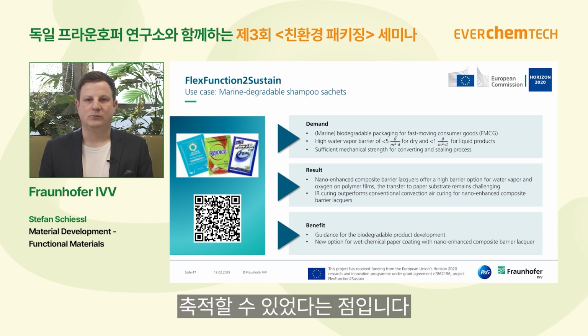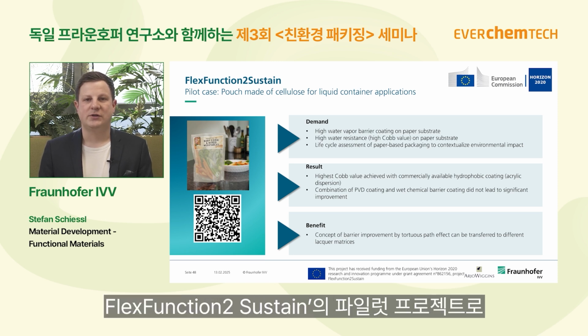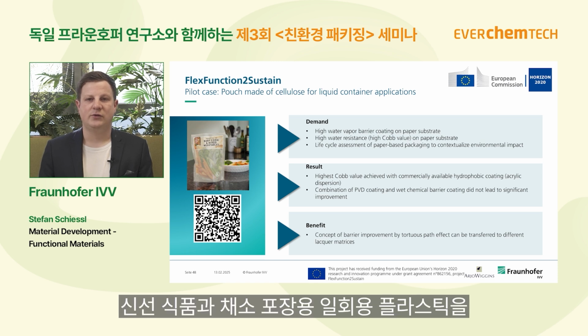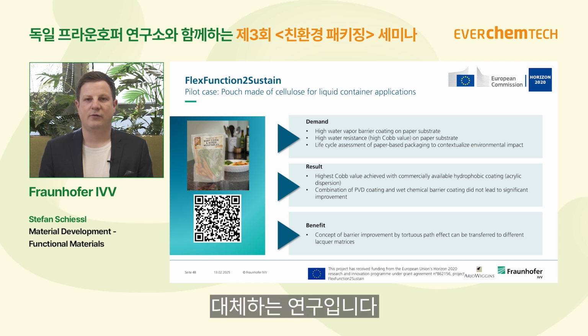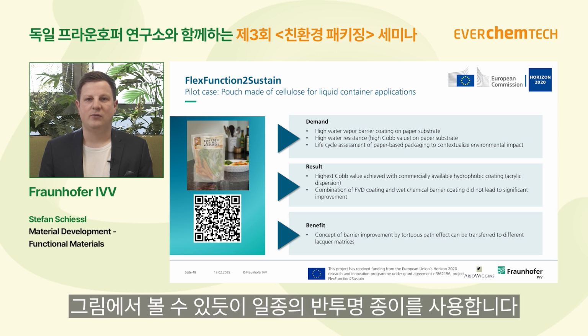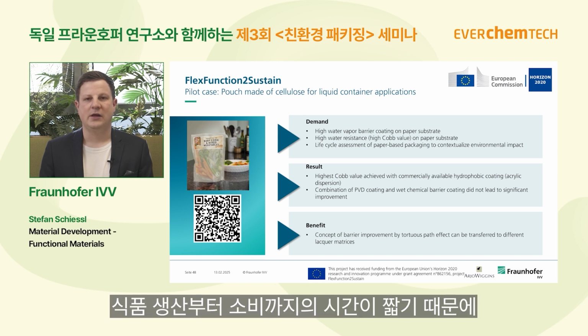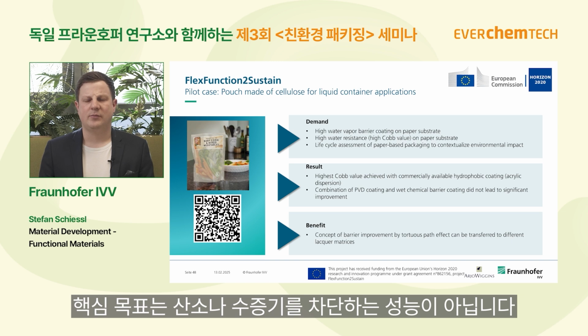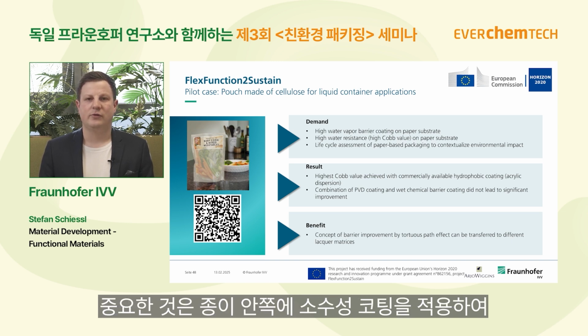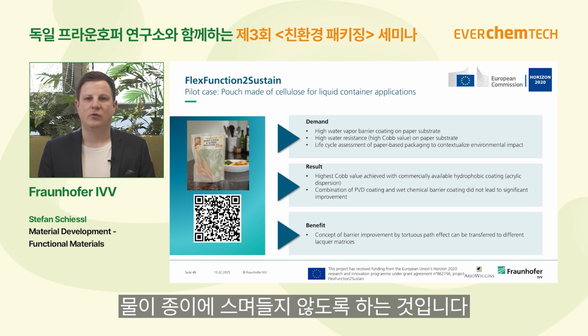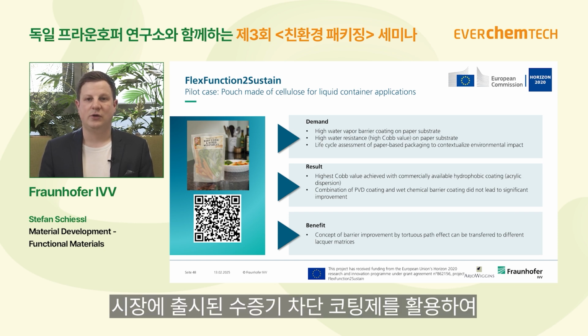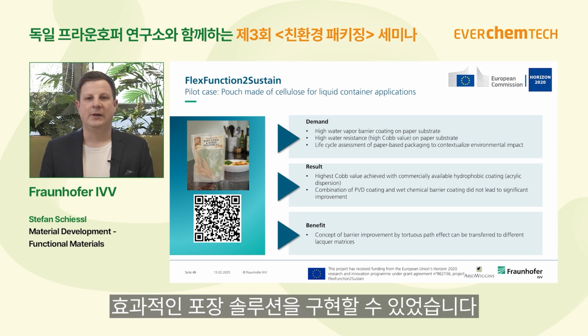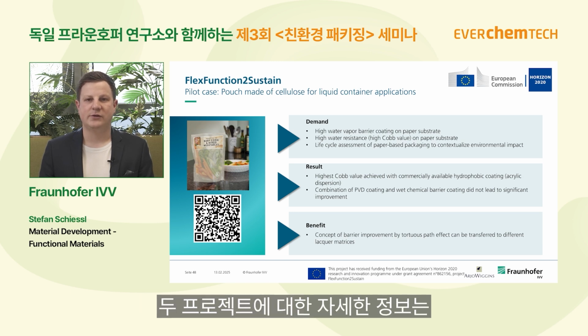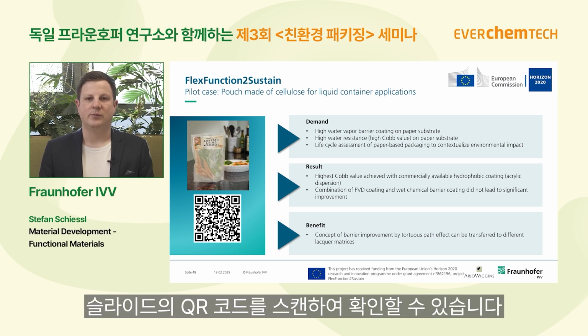And then I have another project which is a pilot case of the Flex Function to Sustain project. Here we wanted to substitute single-use plastics for fresh foods and vegetables, and this is done by a paper which is kind of transparent, as you can see on the picture. Since the time from the creation of the food until the usage of the food is very short, it's not about the barrier against oxygen or water vapor. It's more important to have a coating at the inside of the paper which is hydrophobic, so that no water permeates through the paper, and this we could reach with a market available barrier lacquer against water vapor. And also here we find a very good solution. If you're interested in more information on the two projects, please scan the QR code given on the slides.